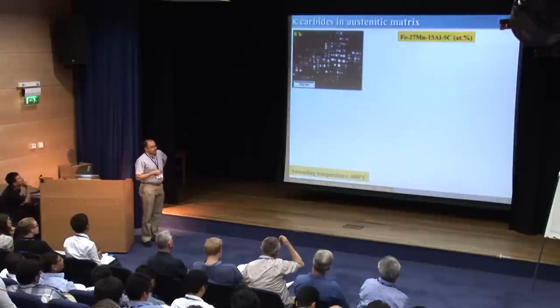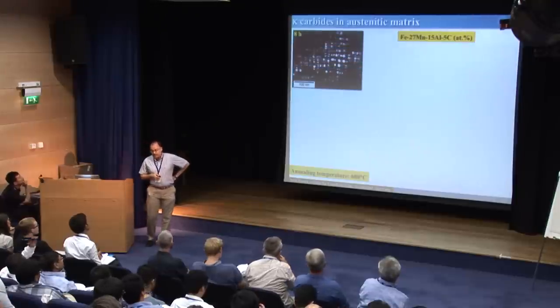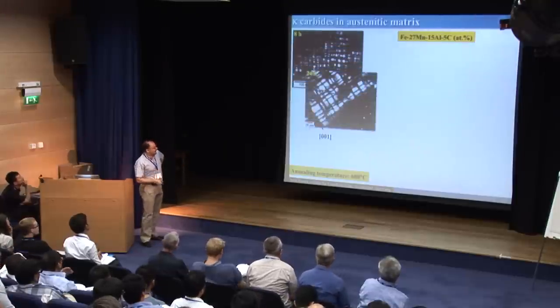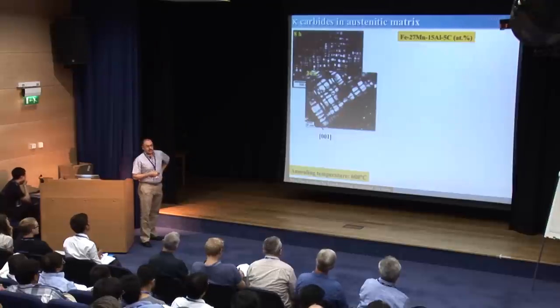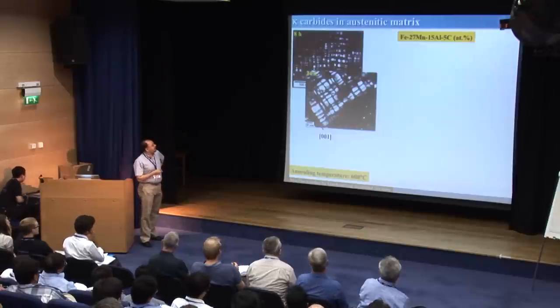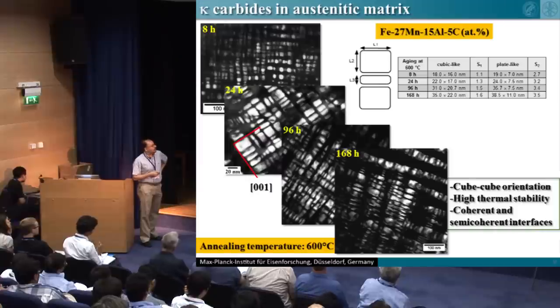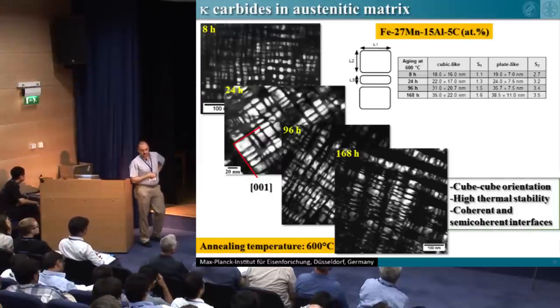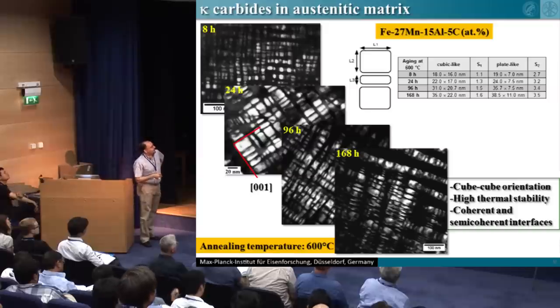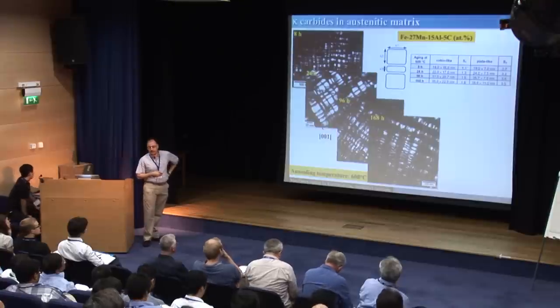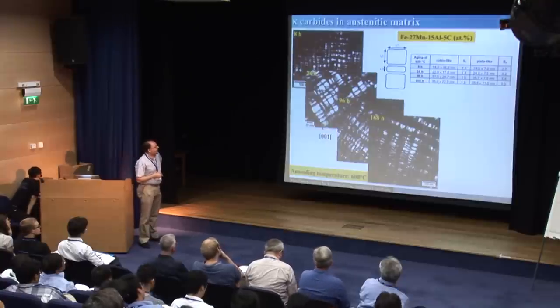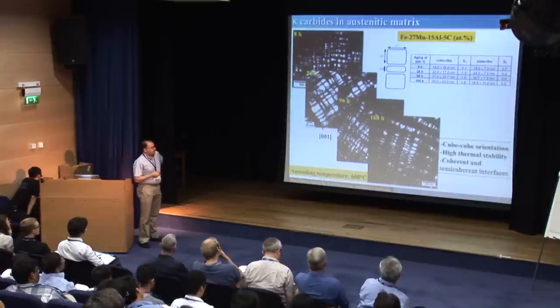in atomic percent, highly alloyed again. The formation of the kappa phase is like this at 600 degrees, at different annealing times, nano-sized. Cuboidal plate-type particles are formed, arranged into what we can call cigars. And you can see the size of these nanoparticles. After 1 week at 600 degrees, they have only increased up to 30, 40 nanometers in size. They follow a cube orientation.